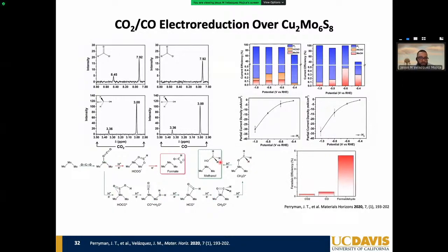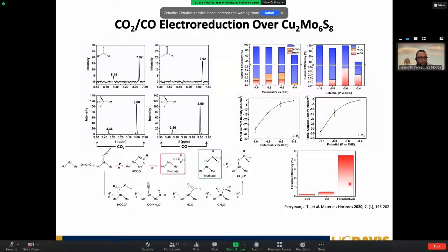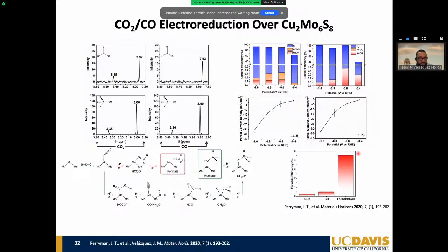So when we saw this, we said, we might be able to do a little bit more digging. Actually, this is something that is ongoing right now in my lab. We changed from CO2 to CO. How about if we produce formaldehyde in situ by the depolymerization of paraformaldehyde? Indeed, when we do that, we are jumping a couple of steps into the steps where we have formaldehyde bound to the Mo6S8, and we see an improved Faradaic efficiency. So this conversion reaction, showing CO2, CO, and formaldehyde, is perhaps giving us strong evidence that the carbophilic pathway is favored.